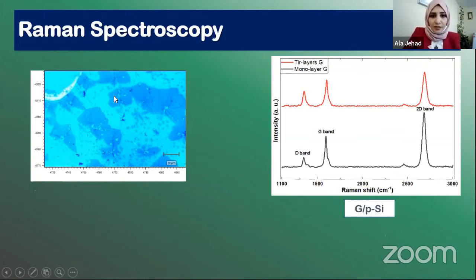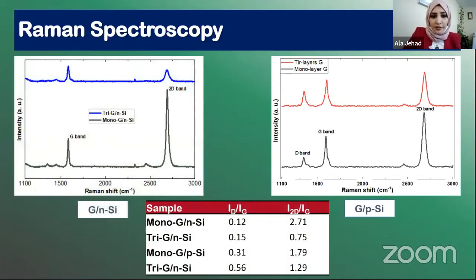Multilayer being 2 or more. To make sure about Raman spectroscopy, we need to measure 2 feature intensities, the first of which is defect intensity. As you can see here in monolayer graphene, when we transfer it on the N-type silicon, we got very low defect intensity, and at the same time we got a number which indicates producing high quality monolayer graphene. Here we have the thickness layer intensity 2.7, which indicates the monolayer. When we transfer graphene 3 times on the sample, we got I2D over IG of 0.75. And the same happens for P silicon and N silicon. We are checking only the defect density of the graphene and the thickness layer ratio of the graphene layer on the substrate.